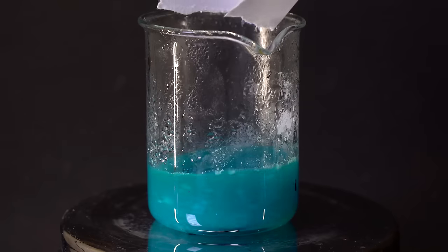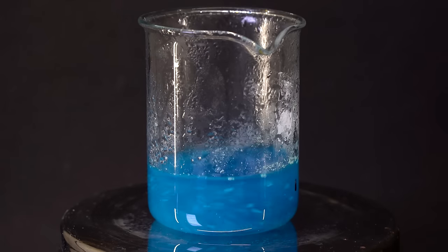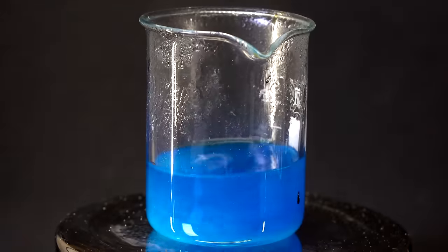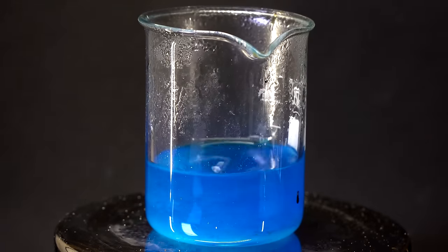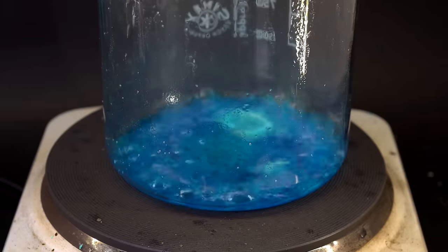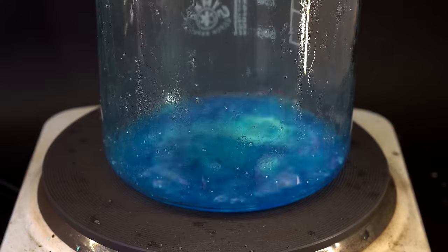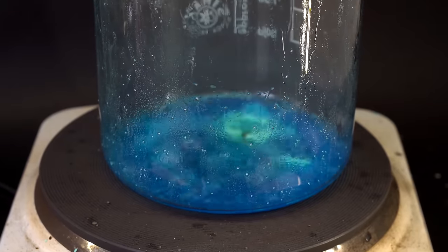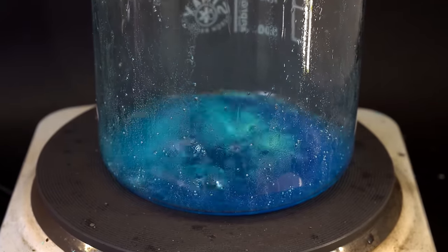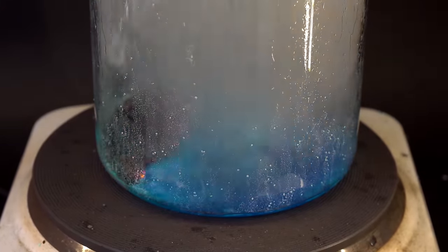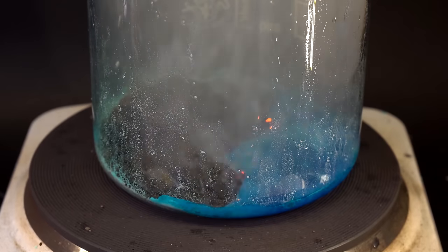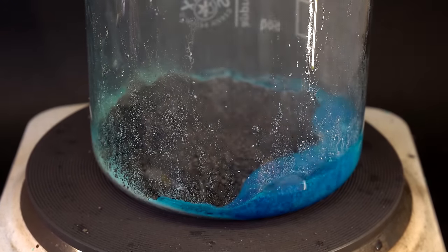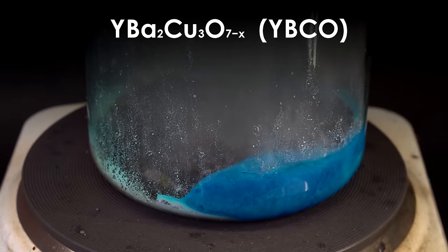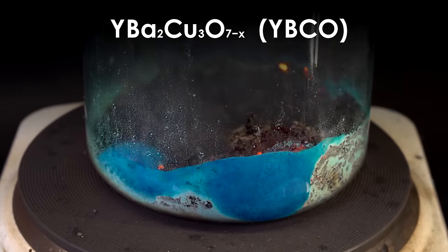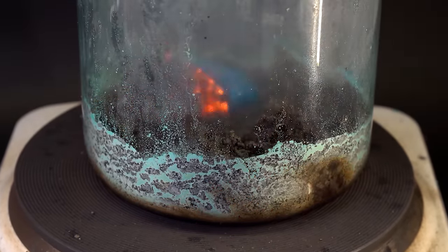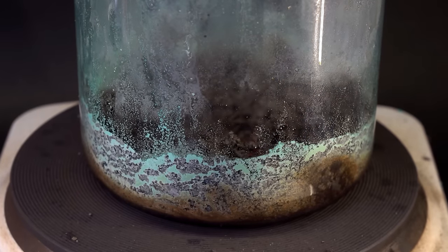For further synthesis, I add citric acid to the mixture, after which the color turns a dark blue because of the copper complexes. Now all that's left is to evaporate the rest of the water out of the solution and wait for the nitrates to react with the citric acid, triggering the so-called pyrosynthesis, in the process of which a mixture of nitrates of different metals will form a mixture of yttrium, barium, and copper oxides, which is known by the abbreviation YBCO. This process is unusual but spectacular.